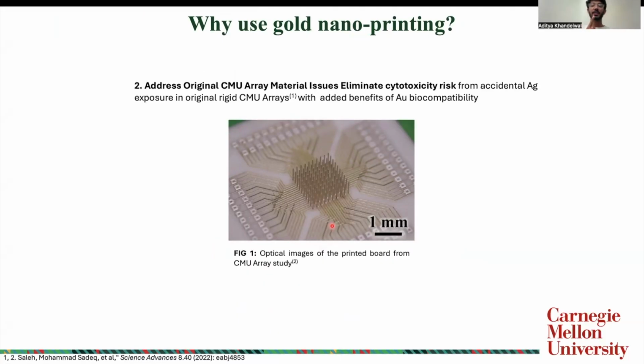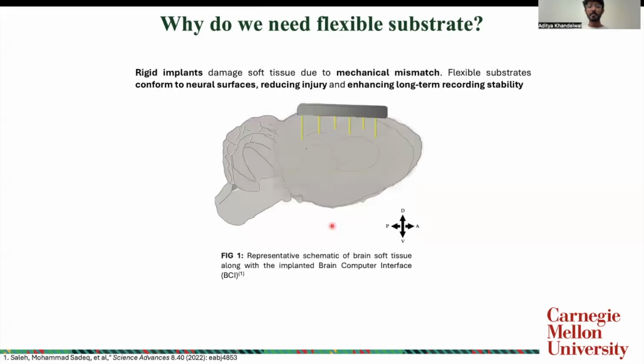First, we eliminate the cytotoxicity risk from accidental silver exposure in the older iteration of the CMU arrays. Second, gold offers excellent biocompatibility while retaining good electrical performance. Third, the flexible substrate. Rigid implants like silicon probes cause tissue damage because they mechanically mismatch with the soft brain tissue. By printing electrodes on a flexible Kapton substrate, our devices conform to the neural surface, reduce the chance of injury, and improve long-term recording stability.